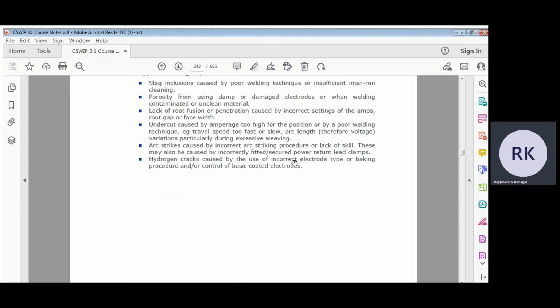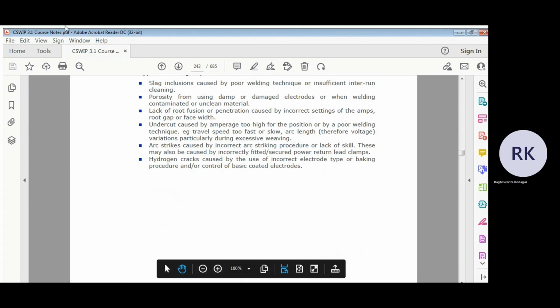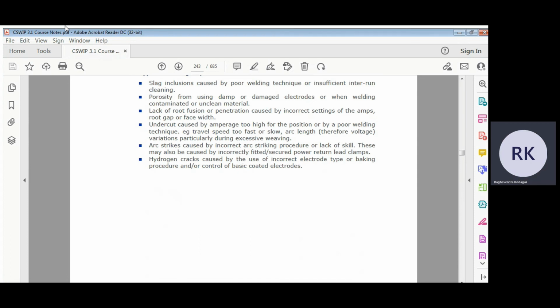Hydrogen cracks caused by use of incorrect electrode type or baking procedure, control of basic coated electrodes. So hydrogen cracks, why do they come? Because if your procedure to control the electrode is not strong, then obviously the electrodes will not be good quality. Then on the fit up you will see some water or let's say grease or oil, then things will get problematic for the welding. Then also hydrogen cracks can come.